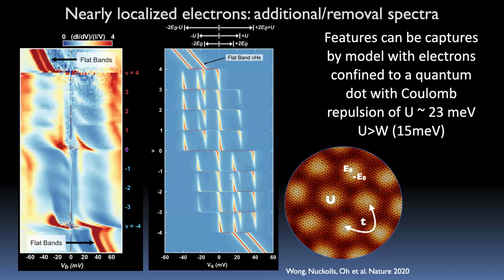So the first thing we did was make the dumbest model possible, which is to just look at the STM image, and what you see are these red bright spots. It basically tells you, oh, electrons are living here. So just treat it like a quantum dot, with very weak hopping and on-site Coulomb repulsion. This is just a decoupled quantum dot, and you can basically solve this problem. And you have basically two sharp levels in the quantum dots. The two flat bands are just two levels, E0 and minus E0. And let's turn off T, and you have large U.